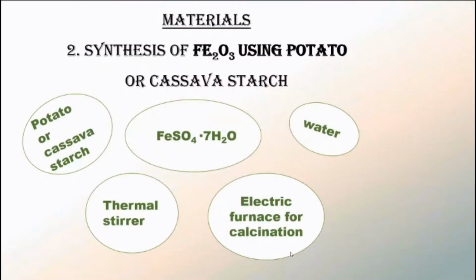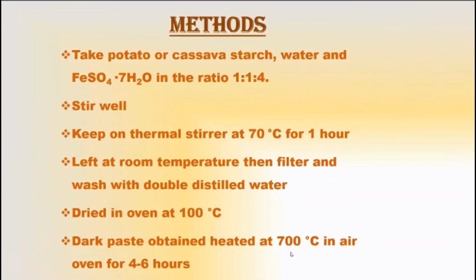The last part of the experiment is synthesis of iron oxide nanoparticles using potato or cassava starch. The materials include potato or cassava starch, ferrous sulfate heptahydrate, water, a thermal stirrer, and an electric furnace for calcination. The method is to take potato or cassava starch, water, and ferrous sulfate heptahydrate in the ratio 1:1:4. Stir well and keep on the thermal stirrer at 70 degrees for 1 hour. Leave at room temperature, then filter and wash with double distilled water. Dry in an oven at 100 degrees Celsius. The dry paste obtained is heated at 700 degrees Celsius in an air oven for 4 to 6 hours.